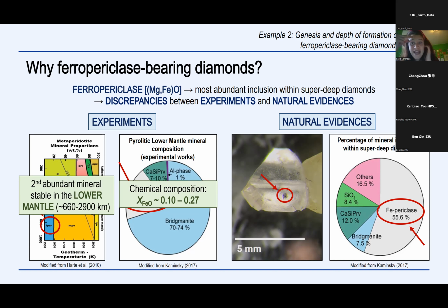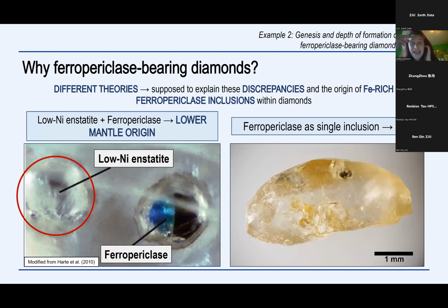But most importantly, the chemical composition of natural ferropericlases is more variable than the chemical composition of the synthetic ferropericlases. And their chemistry can also be very iron rich, with values of iron index that can reach a value of 0.64. Even if in the last decades different theories have been proposed to explain these discrepancies and the possible origin of iron rich ferropericlase inclusions within diamonds, so far we are sure that diamonds containing ferropericlases form in the lower mantle only when ferropericlase is associated with low nickel enstatite inclusions, because low nickel enstatite inclusions are considered the back transformation product of bridgmanite.